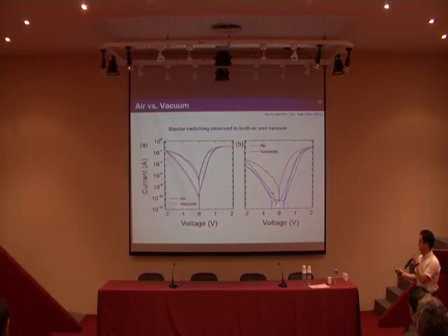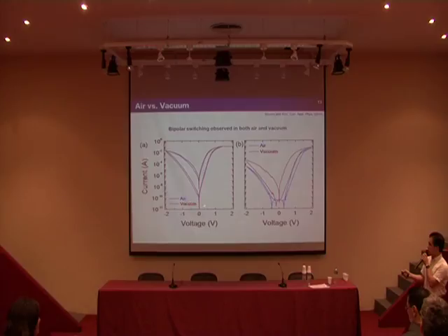Actually, this is like a relaxation behavior. You can see on the left-hand side, there's no dip like this. This is a more conducting sample, so it behaves more like a resistor. On the right-hand side, that sample is more insulating, so we can still expect some capacitor-like behavior. This corresponds to a kind of charging, discharging current.